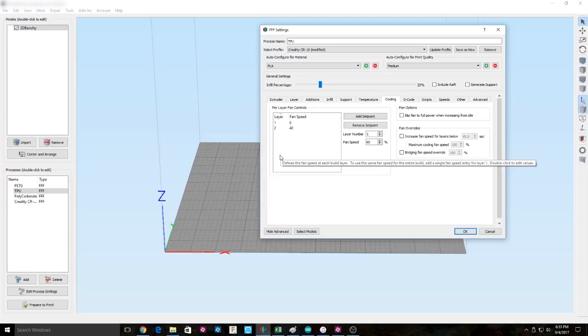I'm using the Fang, so I don't know if that had anything to do with it, but with the stock head, my fan speed was up a little bit higher, about 60%. However, when I upgraded to the Fang, I found that I had to reduce it down to 40% to get the best adhesion, because if I had it at 100% originally, the layers just peeled right off. So I do about 40% and it works good.